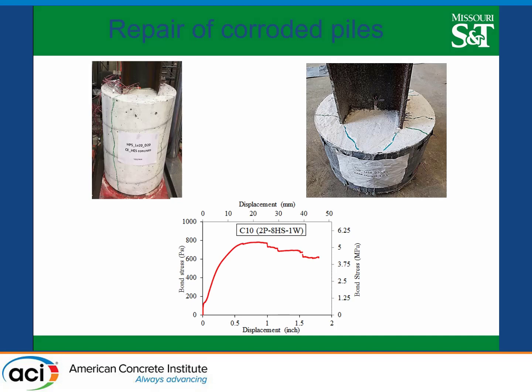This is just to give you a flavor of the results. At the beginning you have a full bond, and everything is elastic. Then you start to get some slip, you reach the peak load, and then you start to have a reduction. The good news is we were able to transfer 100% of the capacity of the pile through the jackets. So this is very much the capacity of the jackets. We yielded the pile without collapsing the jacket itself.